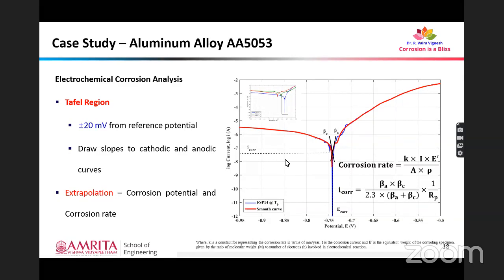Even this Icorr could be found using the slope values, which is given by the equation below. So Icorr is equal to beta A into beta C, where beta A and beta C are the slopes of the anodic curve and cathodic curve respectively, and RP is the polarization resistance value. So even this formula can be used to calculate Icorr, or just by drawing this slope, we can directly correlate with the Icorr and Ecorr values as shown over here. So this is how we calculate corrosion rate and corrosion potential using the potentiodynamic polarization method. I hope we are clear about this concept.